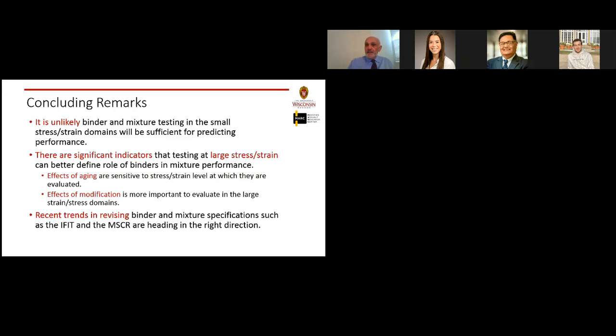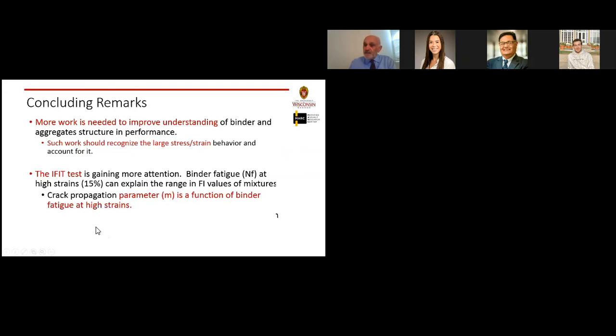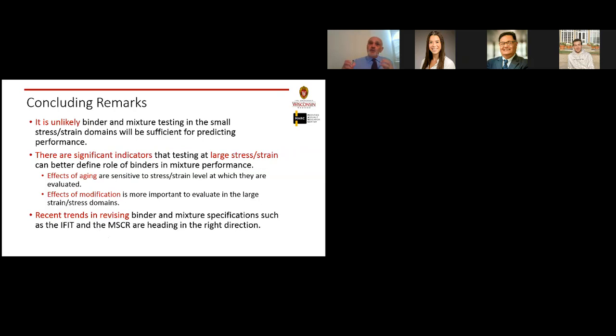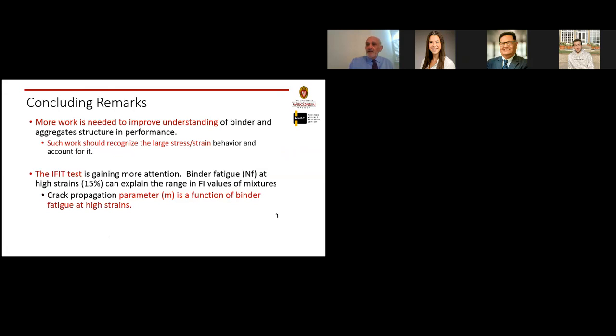So recent trends in revising binder specification, I think, are going in the right direction. I think I will try to encourage people to look at these damage resistance testing, if you will, because I think this will tell us what are the materials that we should be using. Certainly there is more work to improve understanding of the binder and aggregate structure and performance. But at least for the binder, I am totally convinced today that without the large strain testing included, I could be probably misled by the data that I'm doing. So such work should recognize the large stresses and strains.